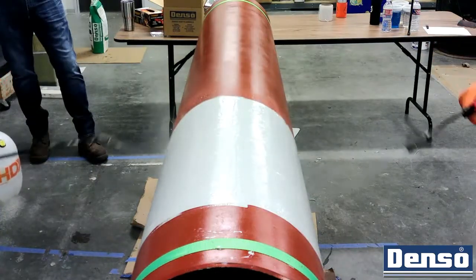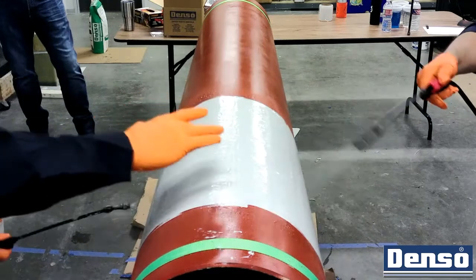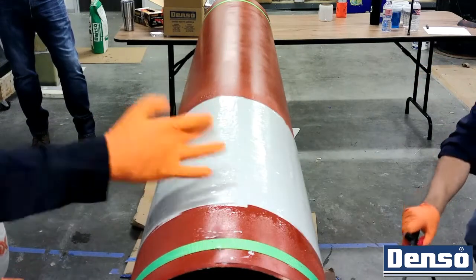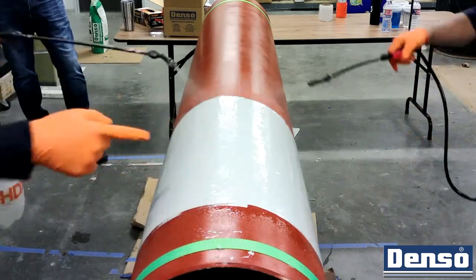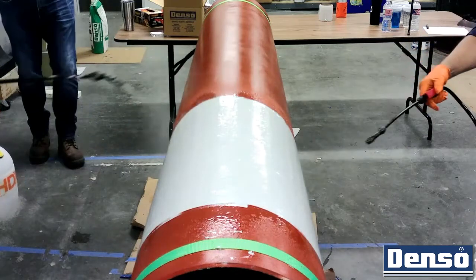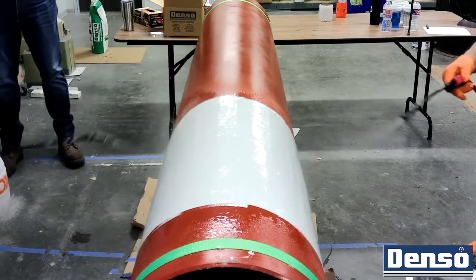Note, there is no such thing as too much water in a bore wrap application. However, an insufficient amount of water can cause the product to cure very slowly and can inhibit the resin from flowing as it normally would.